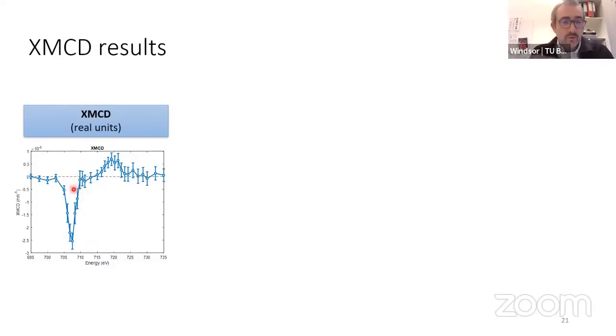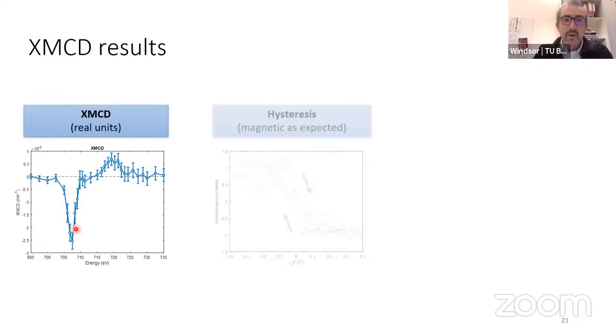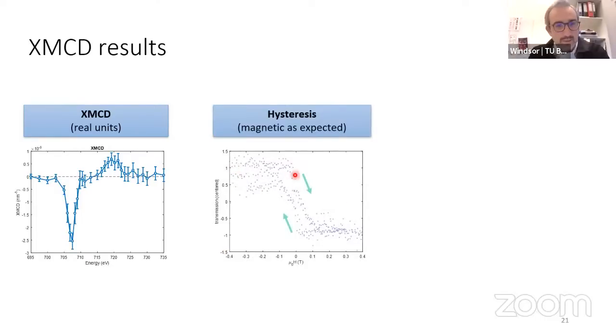And now we want to make sure that this is actually magnetic and behaves like FGT. So we stand here at this energy, 707 eV, and we watch how this contrast changes as we change the magnetic field. And this is shown here. This is not the cleanest data I'd like, but this is also not the purpose of our work. So we can clearly see a hysteresis curve, which is nice, proving to us that this is ferromagnetic.